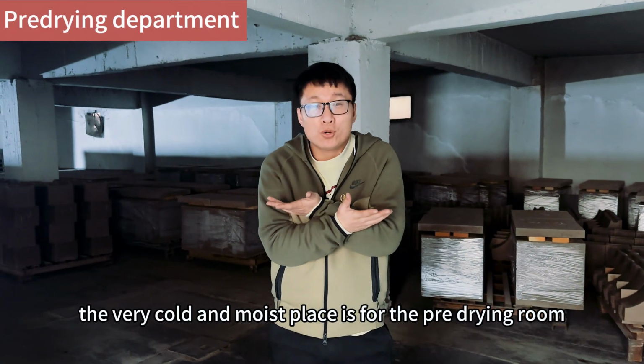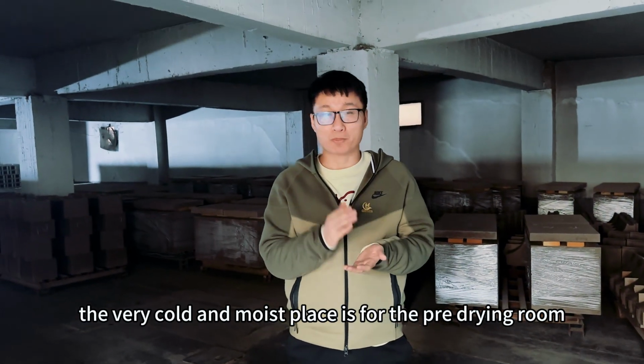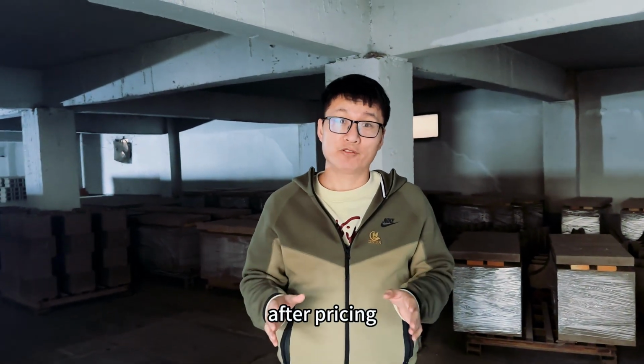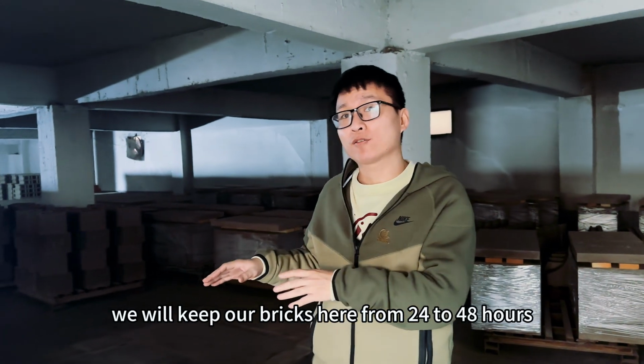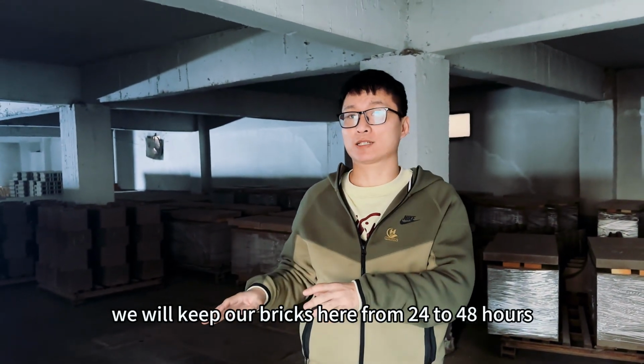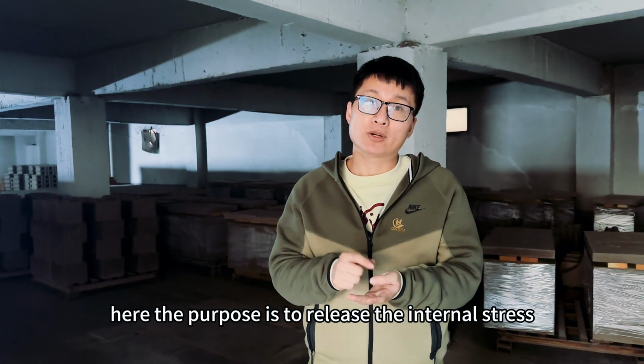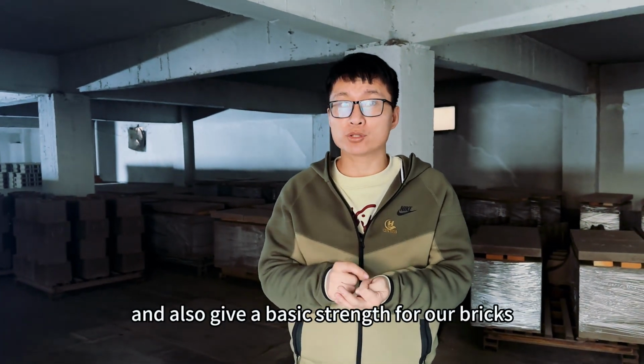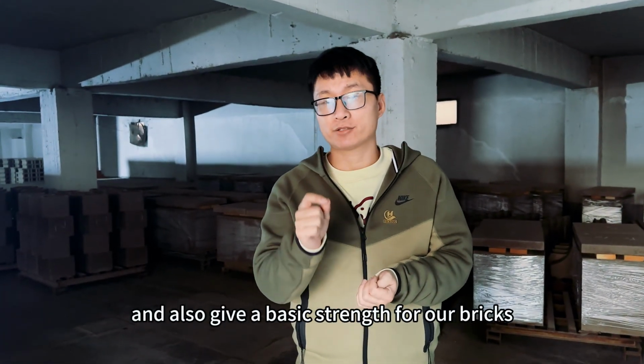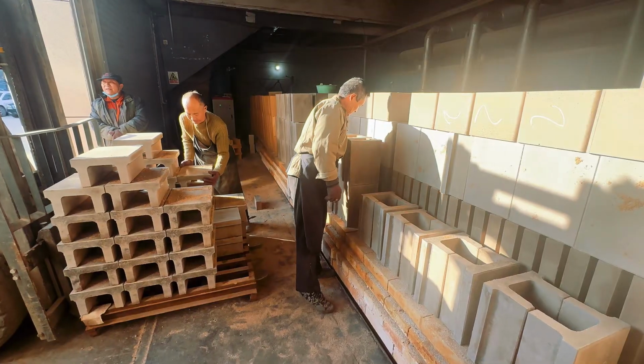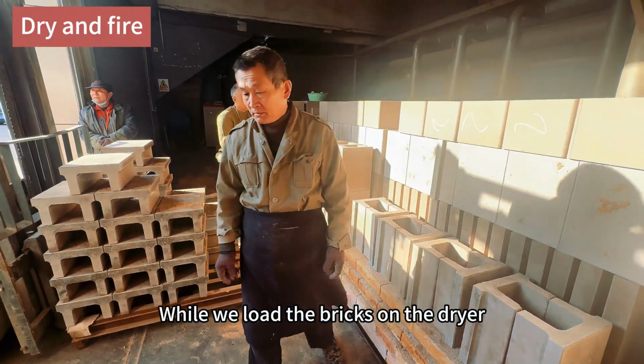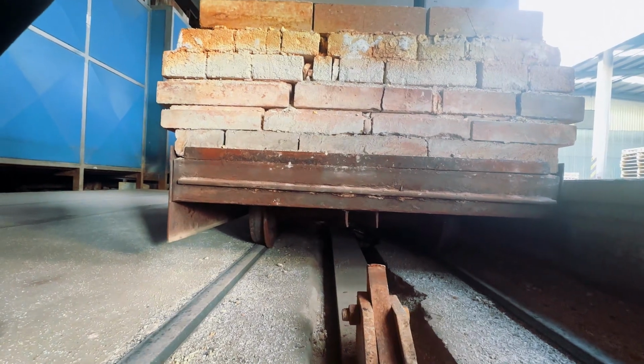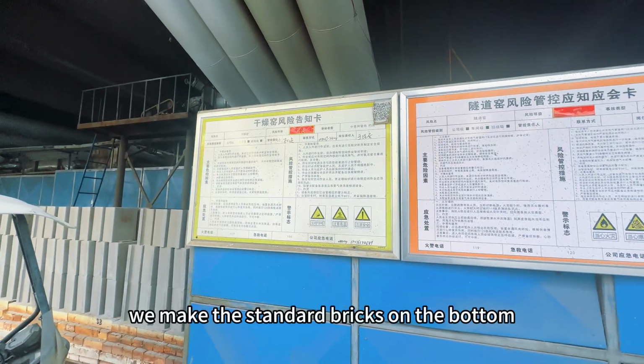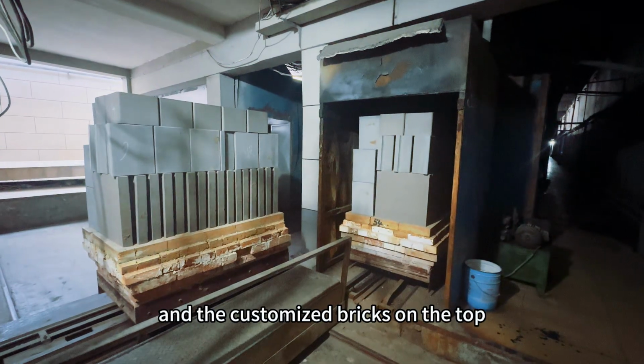This very cold and moist place is for the pre-drying. After pressing, we keep our bricks here for 24 to 48 hours. The purpose here is to release the internal stress and also give a basic strength to our bricks. While we load the bricks on the dryer, we put the standard bricks on the bottom and the customized bricks on the top.